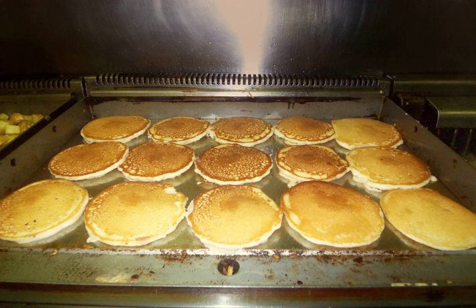Manual. Griddles with manual controls require constant attention by an operator to control the temperature of the griddle plate. Without food products to remove the heat from a griddle surface, the unregulated heat source can cause the plate surface temperature to rise continuously until it levels out at temperatures well beyond those normally used for cooking, over 750 degrees Fahrenheit or 399 degrees Celsius. At these temperatures, the griddle plate material may take on a bluish tint as the surface of the carbon steel plate oxidizes.